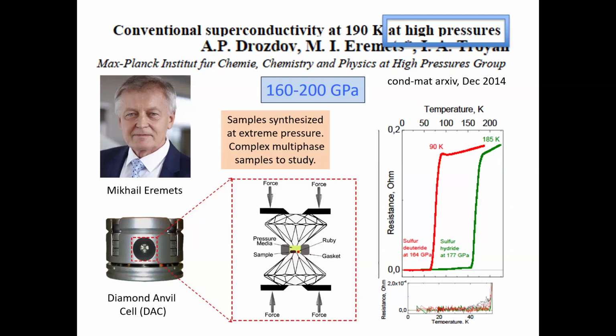All right, and here is what Eremets' group measured, in hydrogen. This is in sulfur hydride (H3S), and measuring the onset of superconductivity of this sample at 185 Kelvin. A better sample was 200 Kelvin. And here is the resistance drop down to zero resistance, the superconductivity drop.